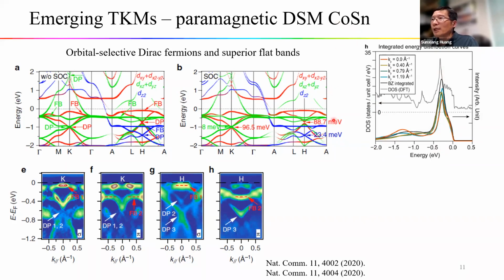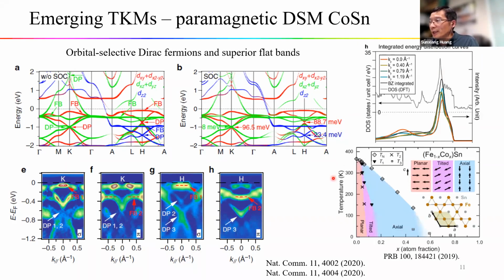Because iron-tin and cobalt-tin are isostructural, they can be doped into each other. So we can get this compound iron-cobalt-tin with composition x from 0 to 1. For x equals 0, we have iron-tin with the planar antiferromagnetic alignment. The moment aligns in the Kagome plane. By replacing about 20% of iron with cobalt, we have this spin reorientation. So the moment actually turns out of plane along the c-axis. Also, this paper and some following work show that there are probably some spin glass states along this region. So anyway, that's another special feature for these 1-1 systems.